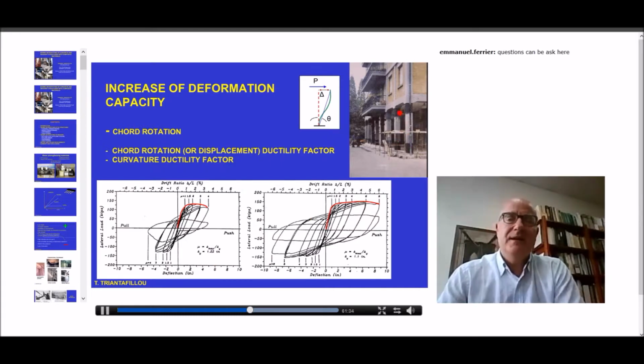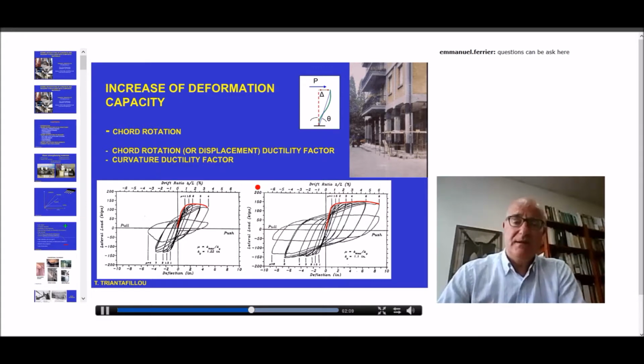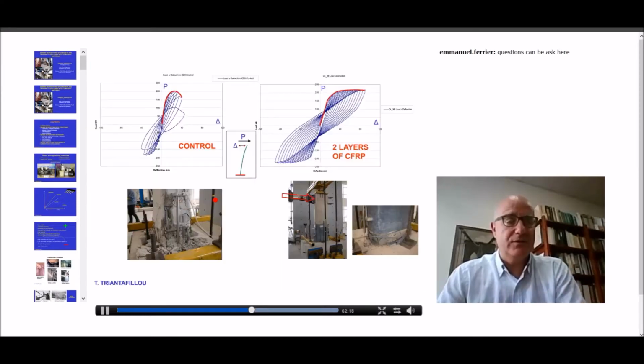This local jacketing is only an effective means of increasing ductility. We only increase the deformation capacity, which can be quantified by the chord rotation. Chord rotation is defined here in this figure, the so-called theta. This is the angle between the axis of the member and the chord of the member at its deformed configuration. So that theta increases. Also the respective ductility factor, mu theta increases, as well as the curvature ductility factor. This is the main reason that we do this local jacketing in seismic retrofitting, to increase the chord rotation or the respective ductility factors.